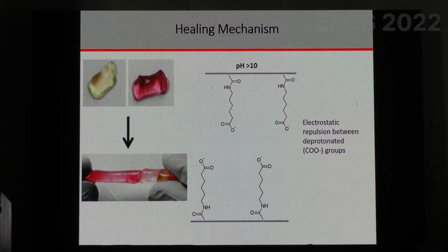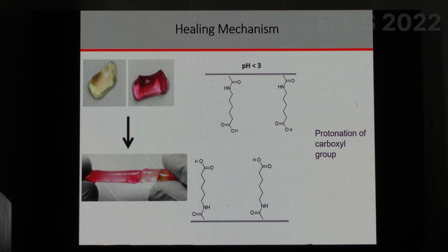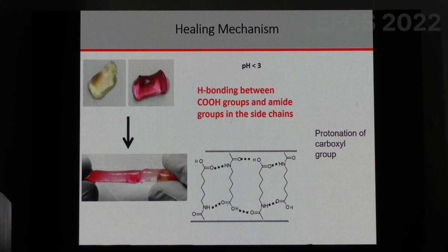And so we started investigating why this is happening. And what we found again is a beautiful evidence of what is happening. You have two polymer chains from across the interface, and they start forming these hydrogen bonds. These are interesting molecules which have this spacer group, the CH2 spacer group. And so they sort of talk to each other across the interface, and they start hydrogen bonding. And we have wonderful simulation evidence as well as spectroscopic evidence to see that actually this happens across the interface. So these spacer groups stretch their arms and start binding to each other through hydrogen bonds, right?